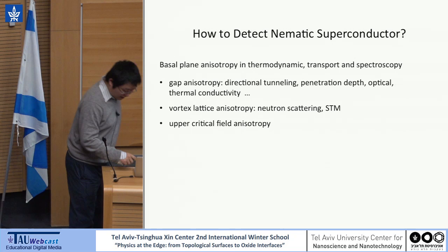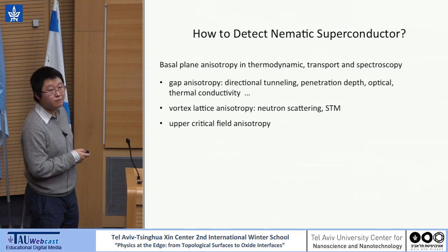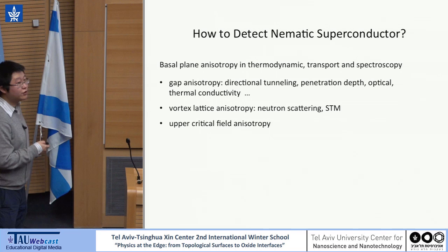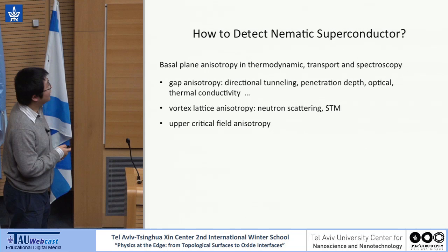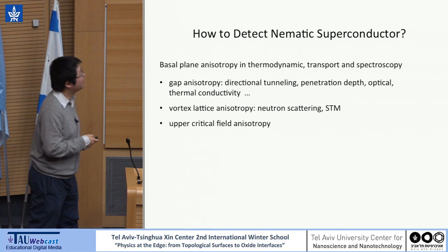Okay, so this NMR experiment gave us strong evidence for nematic order. And I would like to propose some other ways of detecting nematic superconductivity that are perhaps easier. So the nematic order parameter, because it breaks rotation symmetry, leads to a basal plane anisotropy in many thermodynamic, transport and spectroscopy properties. The gap anisotropy can be detected by directional tunneling, by penetration depths, by optical experiments, by angle-dependent thermal conductivity in the magnetic field. Again, when the field is applied, the vortex lattice also can show anisotropy that can be detected by neutron scattering or STM. And I'll spend some time to talk about perhaps the simplest way of detecting nematic superconductivity,